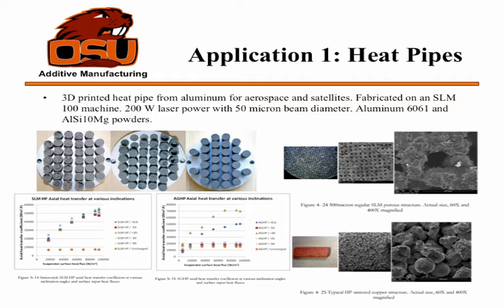And you can see the cool thing, it's a little bit small, but you can see that the SLM heat pipe, which is the ones that go up, are almost entirely independent of inclination angle, which on Earth is a big deal for heat pipes. Heat pipes don't like working against gravity because it's not super high pressure. So with these, they're actually almost gravity independent, which is really nice advantage of the SLM heat pipes.